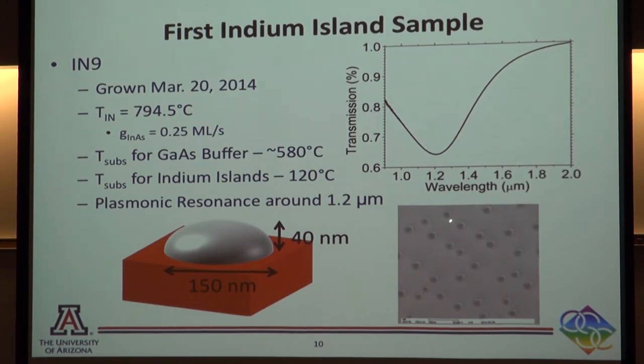We ended up getting islands, and we were even able to measure their wavelengths. It was one of the curious mysteries, which we explained later, that they were all about the same size. It's actually a very nice growth, a Lifshitz-Slyozov distribution of growth, where the big ones grow, the small ones shrink, and the average size is increasing. So we actually measured statistics and saw that in some of these cases we have the flat.